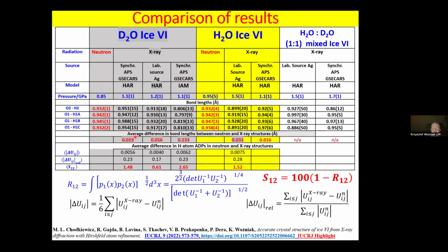And that is helping a lot, because even for laboratory source data for D2O ice VI, and also for synchrotron data from GSECARS, we are getting results very close, very much like those from neutron diffraction. The difference is only as small as 0.019 or 0.016 angstrom. And in the case of H2O ice, we are also getting pretty good data. And not only this, we are getting anisotropic temperature factors, which are in error when compared to neutron